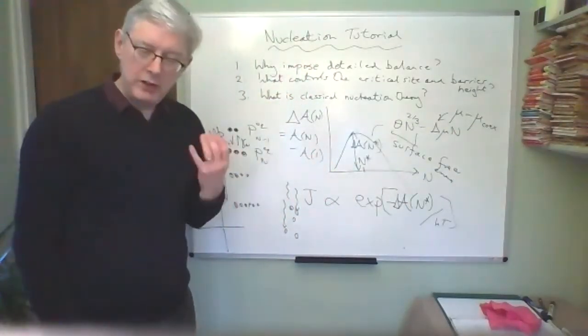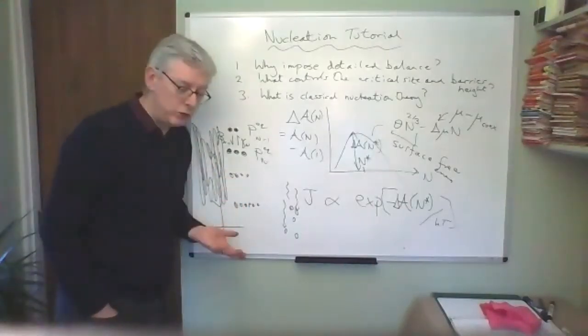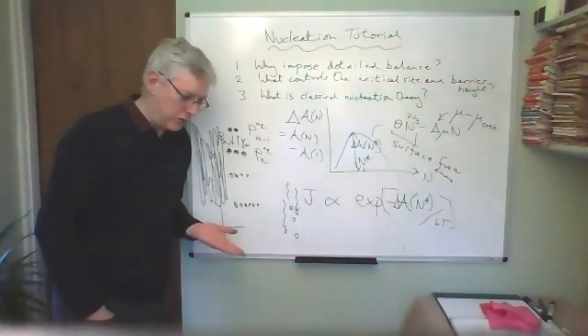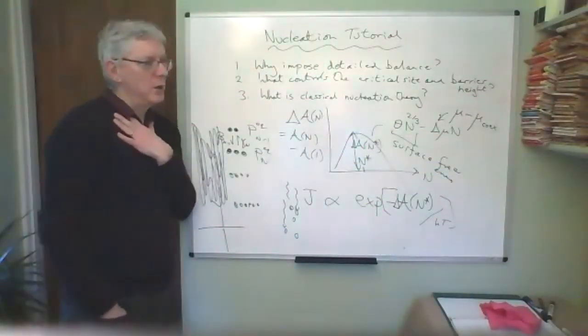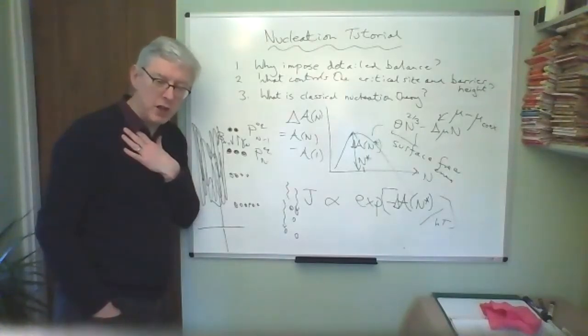So for sure, the gas is not at the same chemical potential as the produced liquid. The liquid is being produced, I guess, at a coexistence chemical potential because it's just liquid. But the gas was supersaturated. It was metastable and had a higher chemical potential. I think that's at the core of your question.